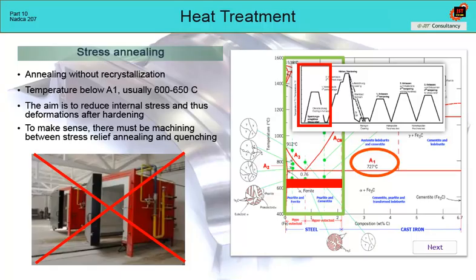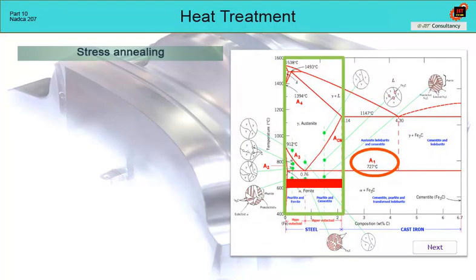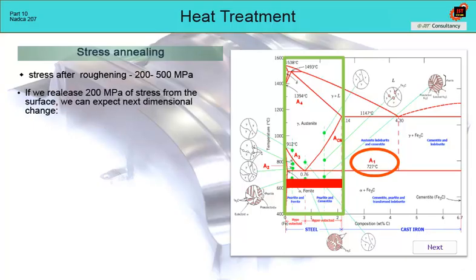Some tool shops try to combine this stress-relieving operation with the process of quenching and tempering, without the intermediate machining operation. Such a procedure does not make sense, because the goal of this annealing, the reduction of distortions during quenching, will not be fulfilled. Because the stresses on the roughed insert are not visible, this operation is often ignored, and one relies on the fact that it will work out somehow, or that the result will have a negligible impact on the deformations. However, it is necessary to realize that after roughing, the tensile stress on the surface can be 200 to 500 megapascals. If we assume that 200 megapascals of stress is released during annealing, then the related dimensional change will be as follows.